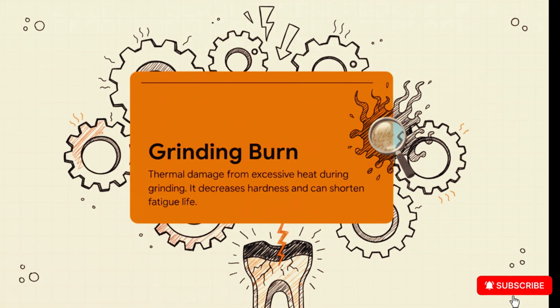But you probably guessed it, this final step has its own hidden danger, and it's called grinding burn. If the grinding creates too much heat, it can actually damage the heat treatment on a super thin layer of the surface. It's invisible thermal damage, and what it does is it softens the steel, and, even worse, it creates these really bad tensile stresses. This can just demolish the gear's lifespan, totally undoing all the good work from the carburizing process.